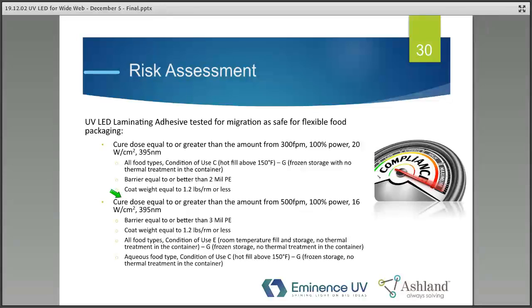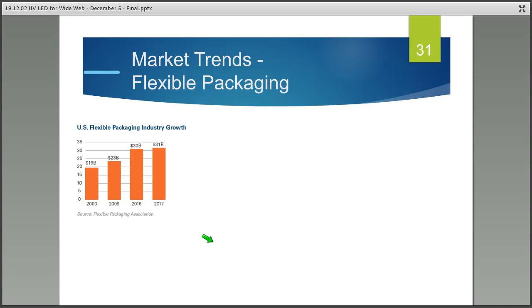Another one that we've cleared recently, dose equal to 500 feet per minute, 100% power, 16 watts per centimeter squared at 395 nanometers. This was a thicker barrier, 3 mil, and again, we could not get to that condition. We were only able to clear it for condition of use G, which is room temperature. So again, conditions are important. You can't just say I've cleared at this level and therefore you can use it in all these applications. You really need to do your homework on this. And I think that's my last slide.